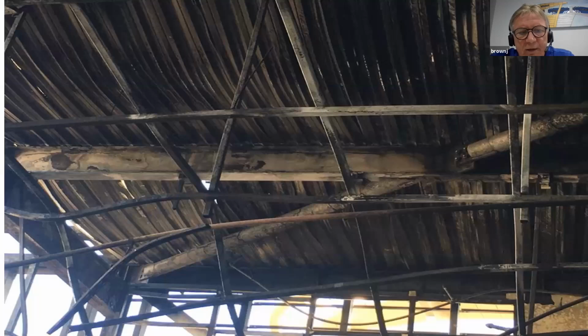But more interestingly, if you look up in there, you can see the trapezoidal decking has buckled and collapsed as the concrete has broken on the floor above. But if you look, the beam is still showing in very good condition. The steel that's bent and warped is the secondary steel, which was probably holding the ceiling up, the false ceiling. So the products have worked absolutely perfectly, and the building could go back into service reasonably quickly.